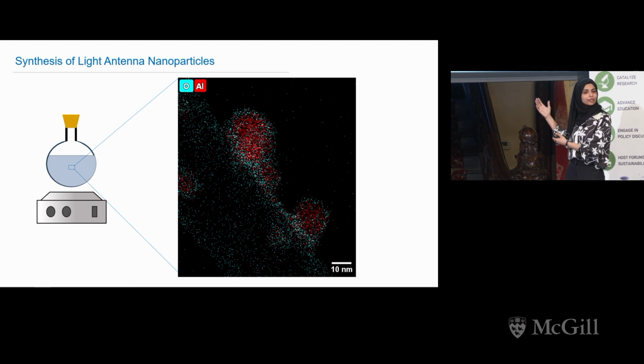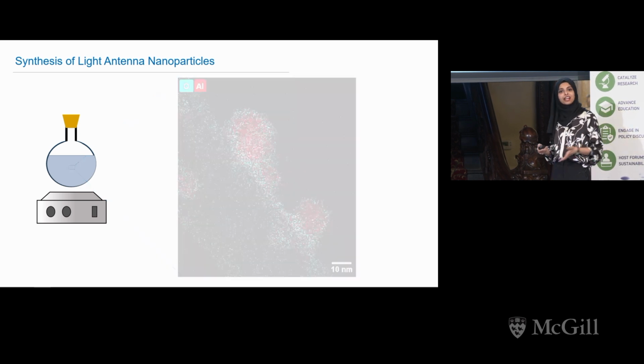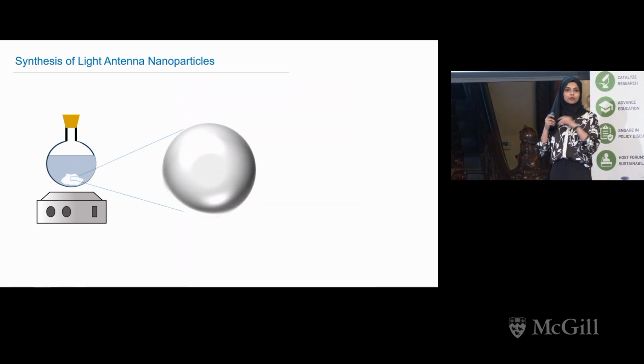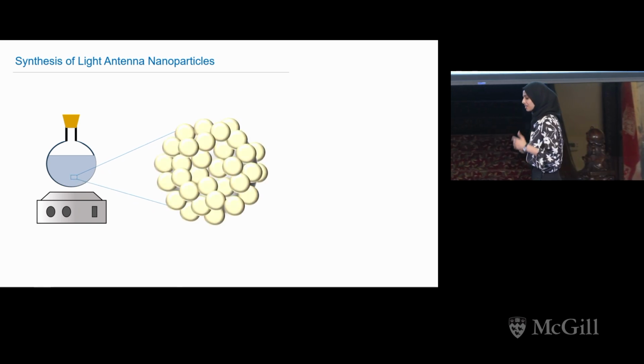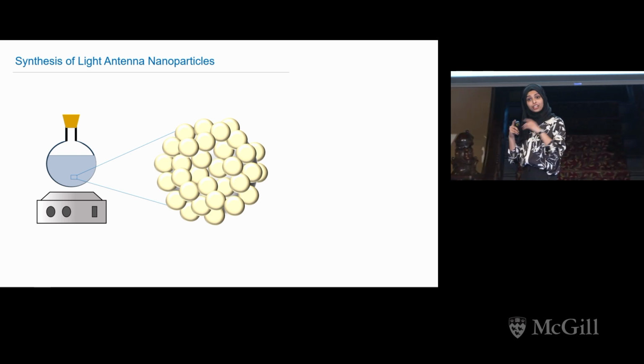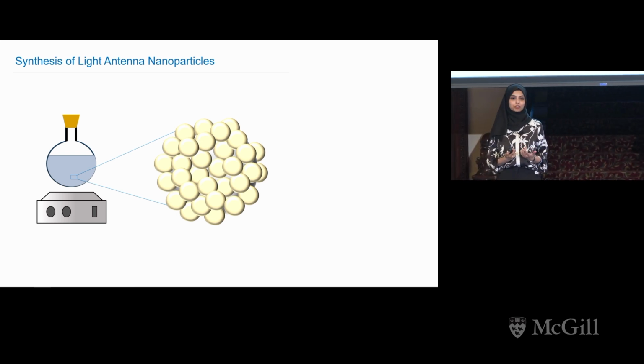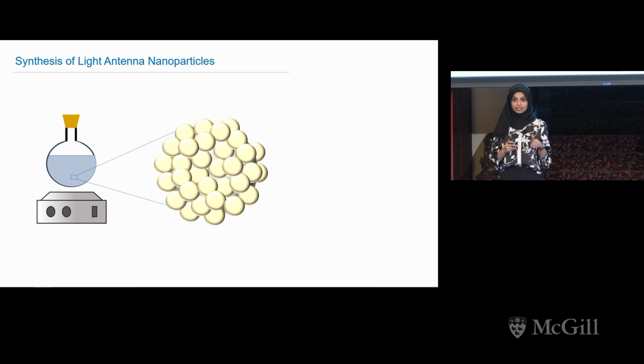Now that I had my aluminum nanoparticles ready, the next step was to attach or couple them with the photocatalyst. I thought, why not place the photocatalyst in the reactor itself and let the aluminum nanoparticles deposit on top of it? That was an option, but not the best thought. That resulted in over-deposition or aggregation of aluminum nanoparticles around the surface of the photocatalyst, which decreased the performance of the photocatalyst, which is not what we wanted.